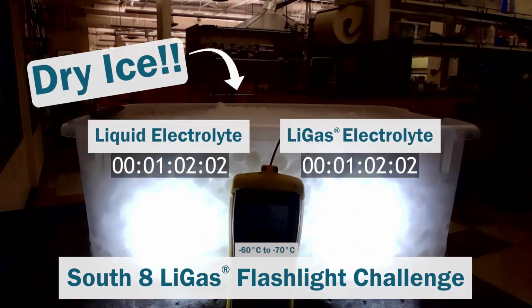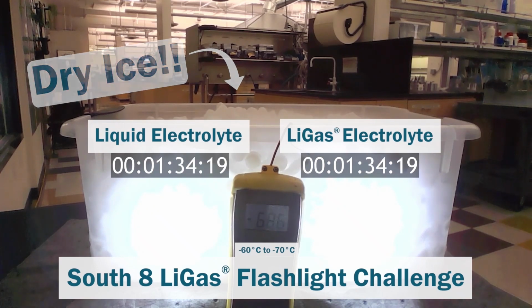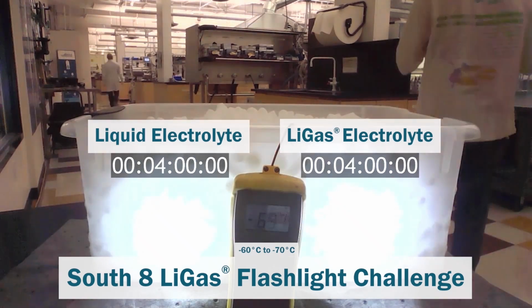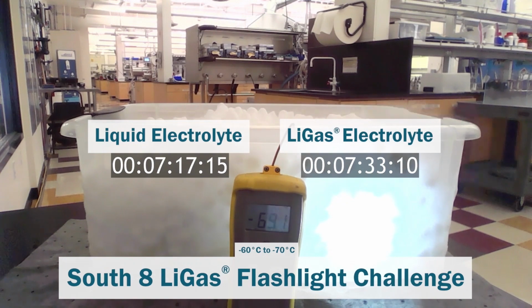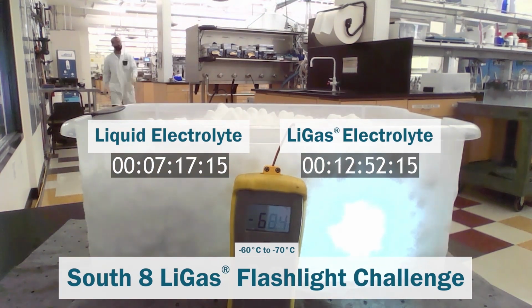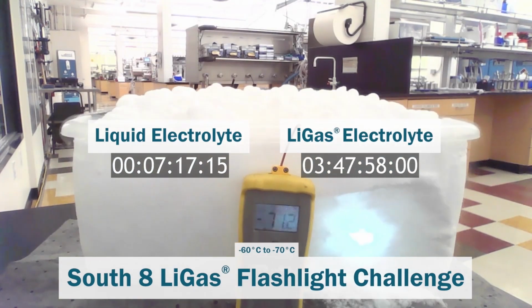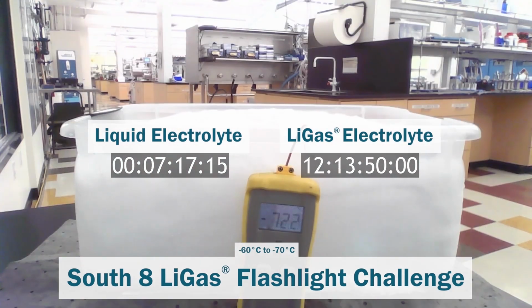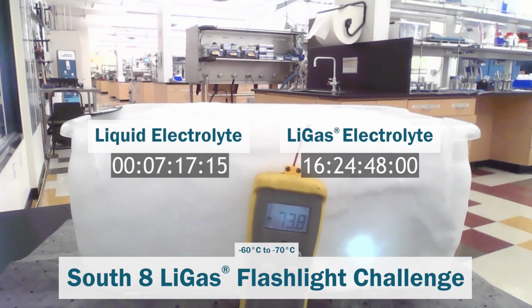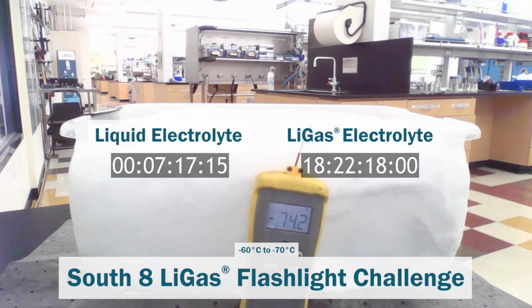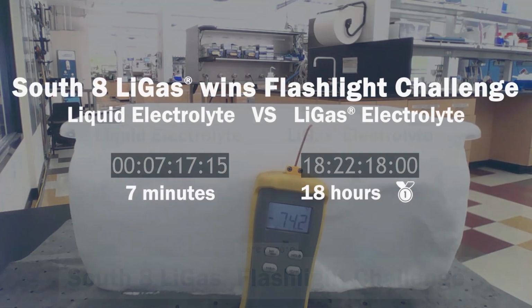And you'll see in a few minutes that temperature dropping to -70 degrees, -80 degrees, and that liquid electrolyte just begins to fill right there. So you see that flashlight turn off after about 7 minutes. That stuff just freezes up, doesn't really give you any performance. The LiGas electrolyte continues throughout the day, overnight, into the next morning, and finally, about 18 hours later, that flashlight finally dies out. Really an amazing technology for anyone that needs that ultra-low temperature range.